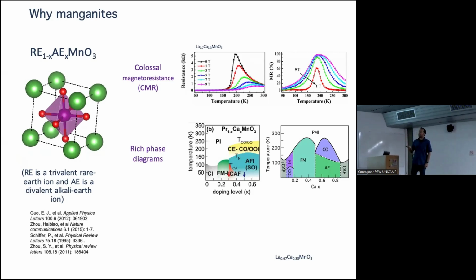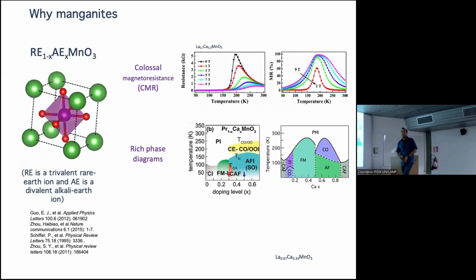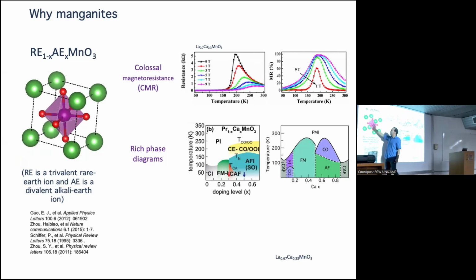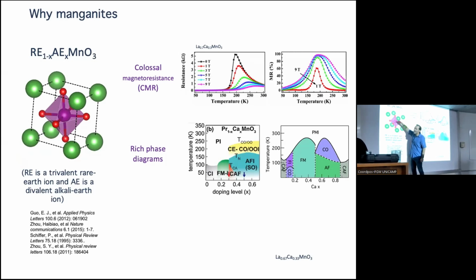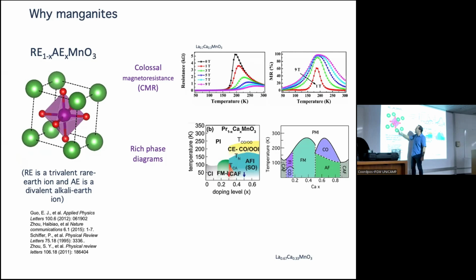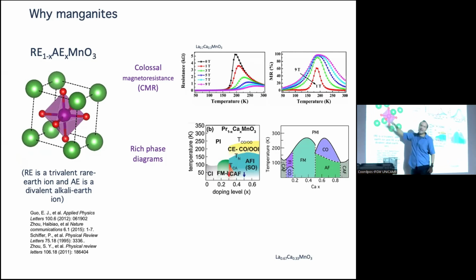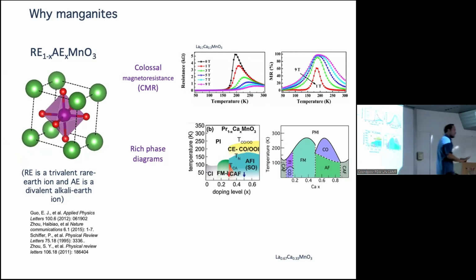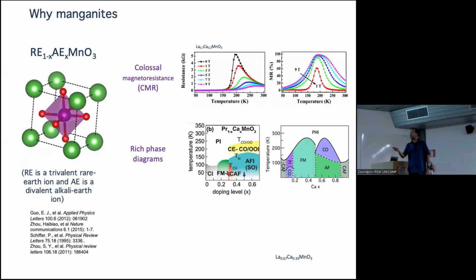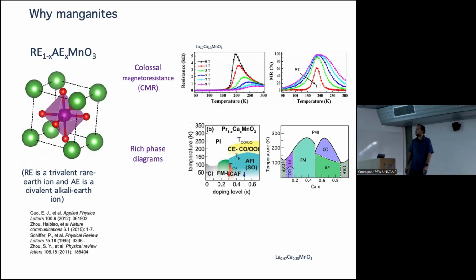The crystal structure here is a perovskite where you can actually change these two materials. You can have a trivalent rare earth ion or a divalent alkaline earth ion. And then you can change this in a way that actually will affect the environment of the manganese, which is in the center. Every physics that happens here, it happens because this octahedra is changing the manganese properties inside. Okay, that's the trick. And then here are the oxygen atoms.